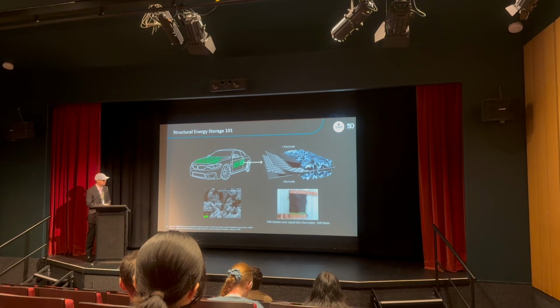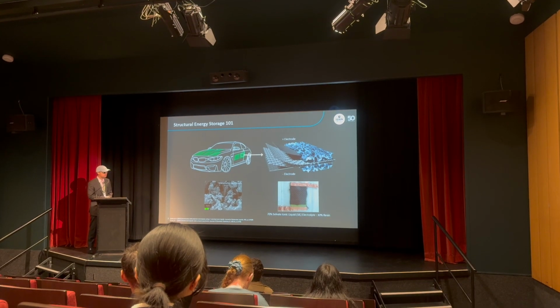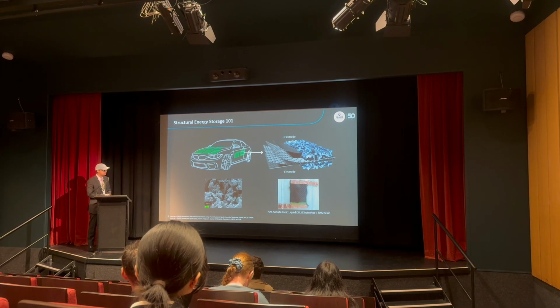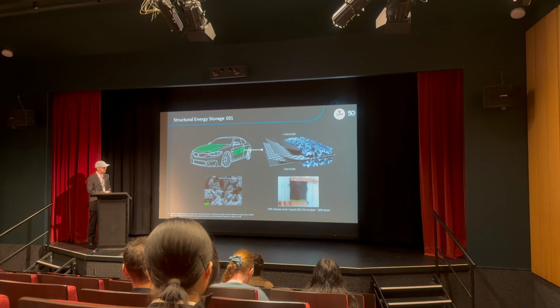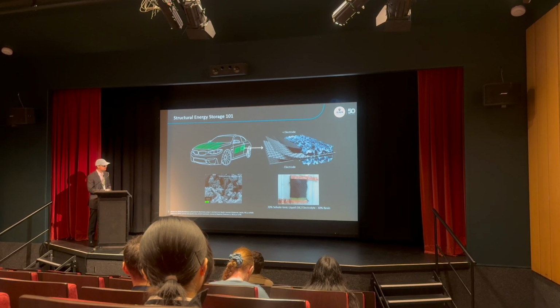At a lab scale, this is what a prototype structural capacitor looks like. The matrix in the system consists of 70% ionic liquid and 30% resin. And this is looking at it from the top, and you can see the conductive carbon fibre electrodes and a glass fibre separator there in the white.